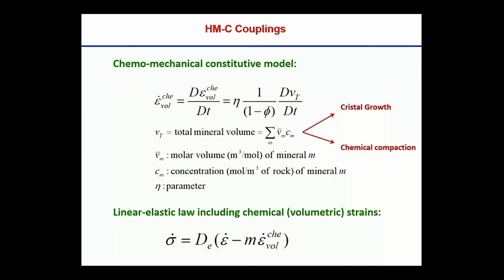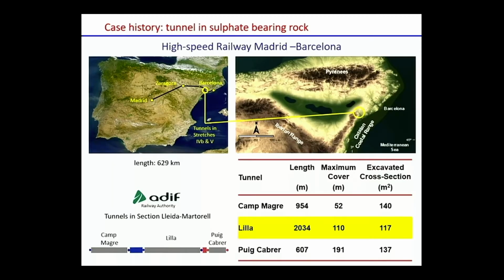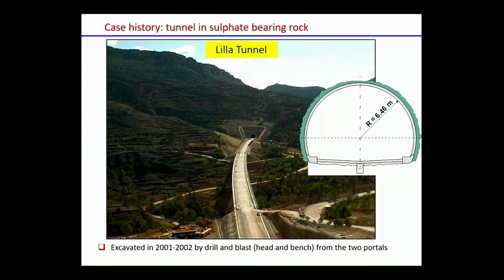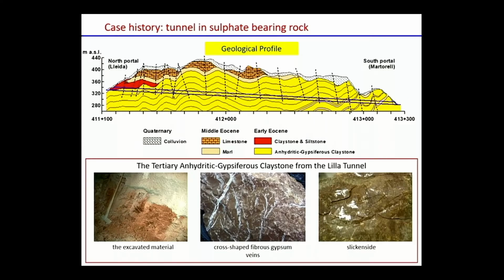So we have to put this in a mechanical constitutive law relating elastic deformations. And I'm going to present two cases, one of swelling of the material and another one for compaction of the material. In this case, this formulation was applied to phenomenologically explain some phenomena that were observed on the high speed railway Madrid-Barcelona. In this case, it is the Lilla tunnel. We have the excavation of a tunnel in argillaceous rock with gypsum veins, and what happened was that the relative humidity inside this gallery increases.